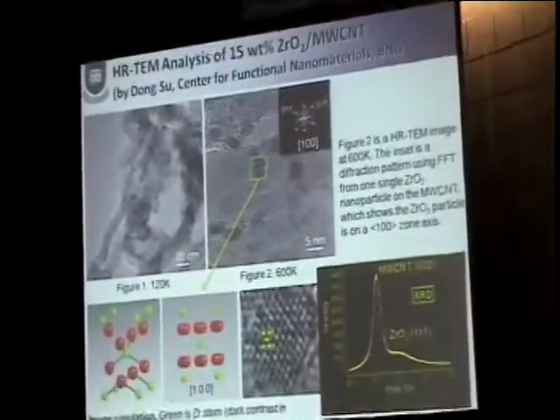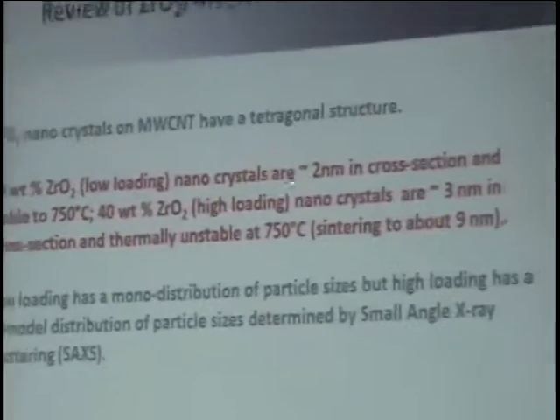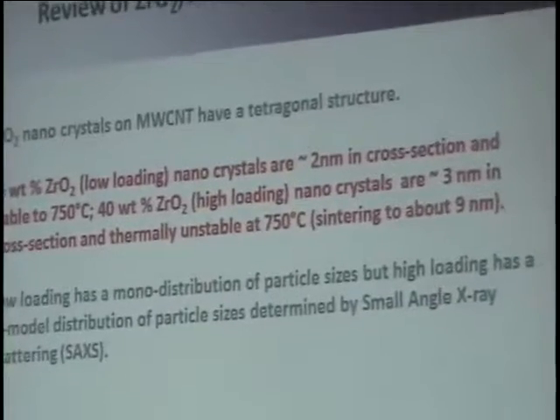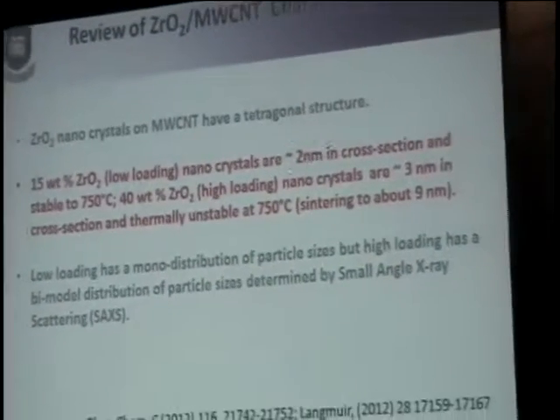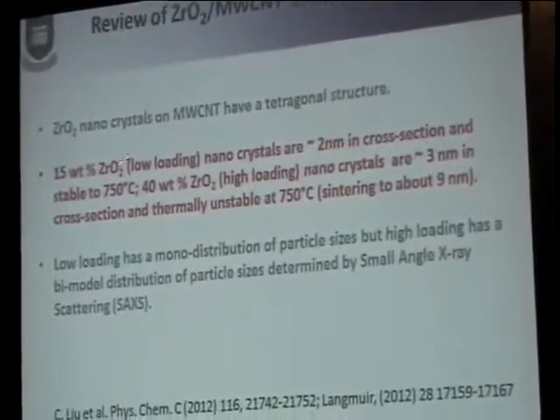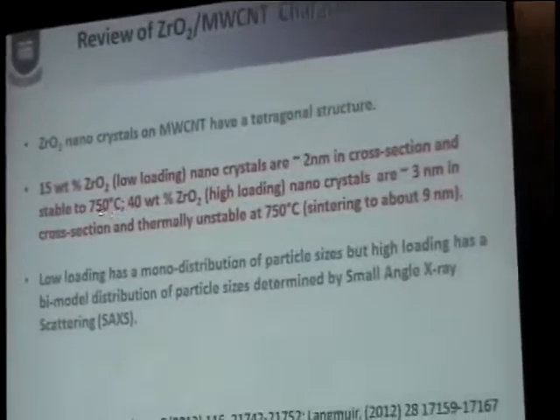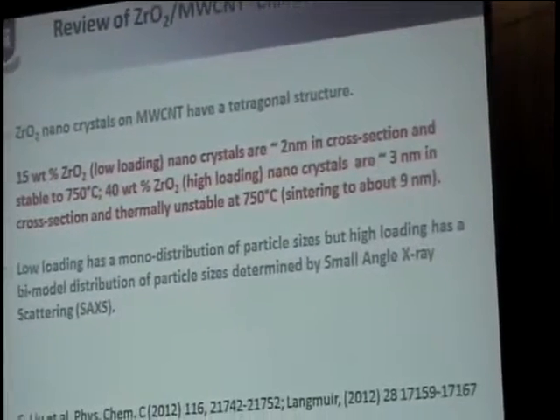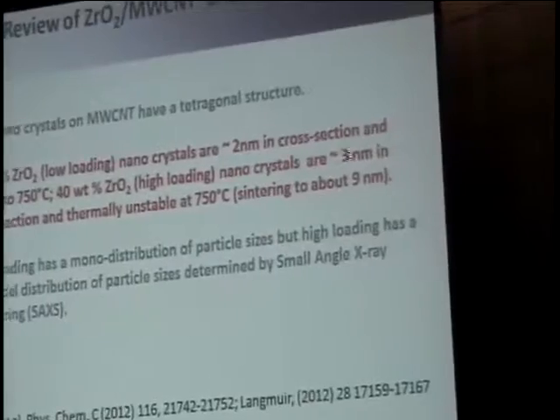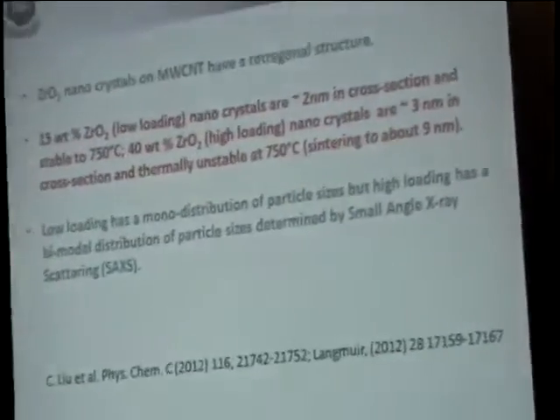So that we know about it, which is not different than the bulk. The next thing I want to say is that we are going to focus our attention on weight loadings around 15%, because only in that range do we have thermally stable small particles in the range of 2 nanometers. That means stable up to about 750. At higher loadings, you get a larger particle initially, and they are unstable towards thermal sintering.